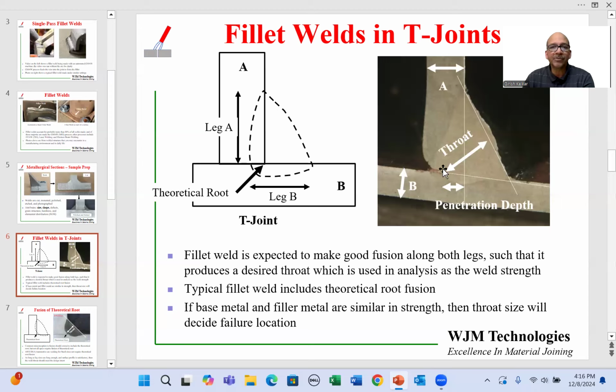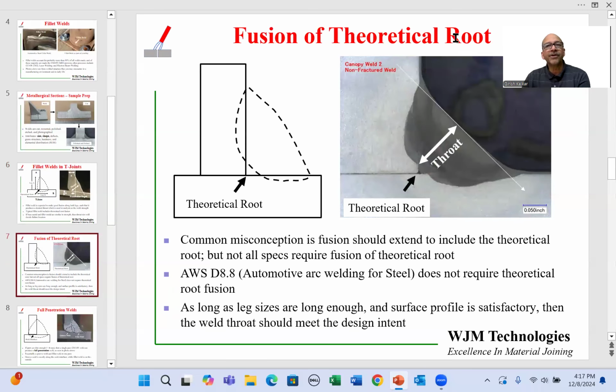So this is a very typical cross-section of a fillet weld. We are seeing the theoretical root has been fused, and there's a decent amount of leg on both sides that will give you the required amount of throat. But the fusion of the theoretical root is not so simple. Here I'm showing you a cross-section where the theoretical root has not been fused. We can see the fillet weld. We can see leg A and leg B, but there is no fusion at the theoretical root. And I'm showing you the same on the left in a schematic form where the theoretical root is not fused.